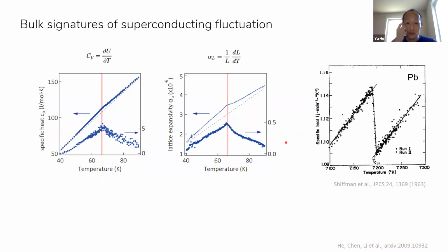Yeah, right. So this is something very peculiar, and we think could be a generic electronic correlation that sets the low energy electronic structure landscape. We may call it a kink, but if we really look at the dispersion, it's continuously bending down. It just bends down quicker and quicker until it plummets to the gamma point. So it's not really like an electron-phonon coupling kink in our conventional understanding, sharply centered around an energy. Everything just evolves continuously, but it plummets faster.